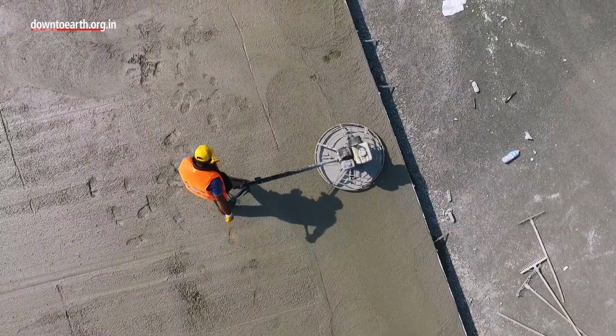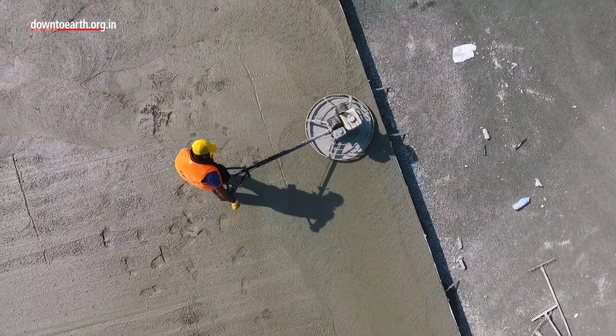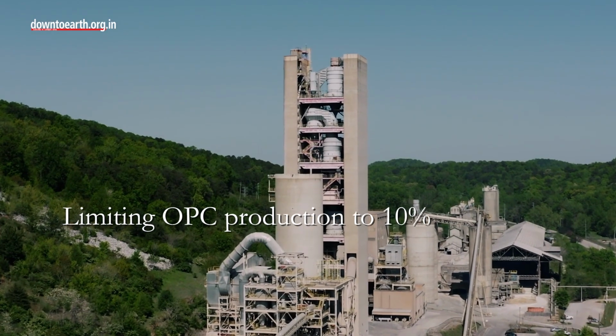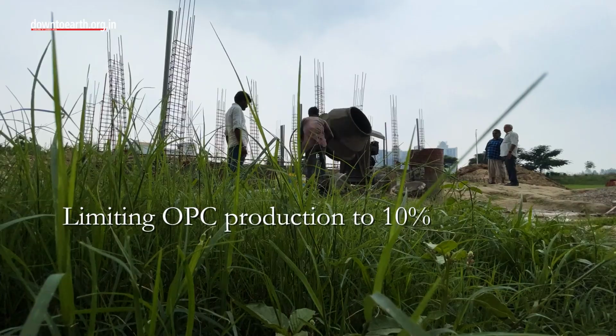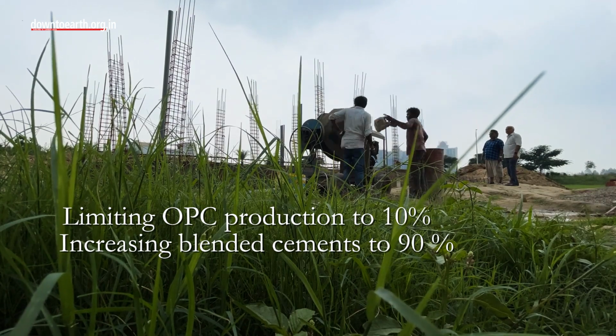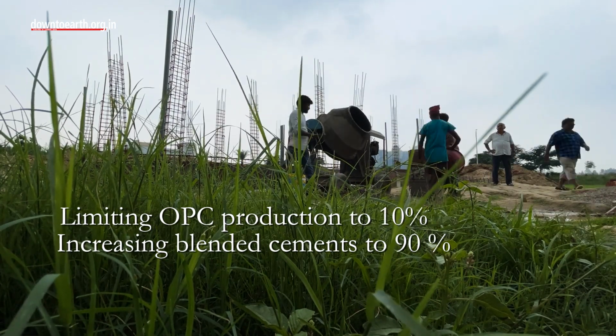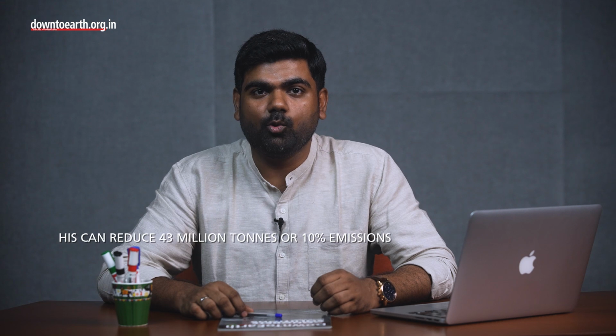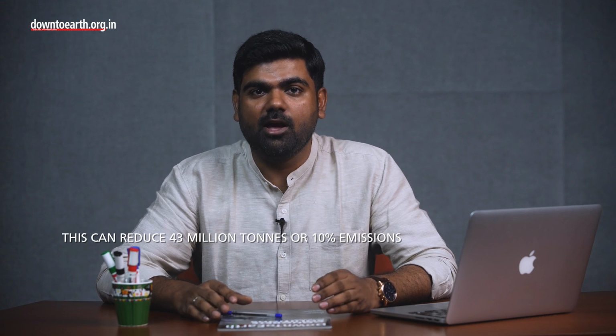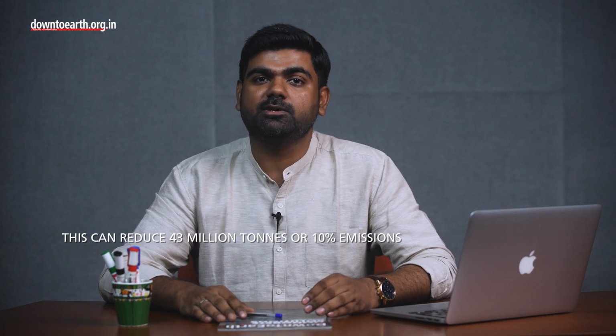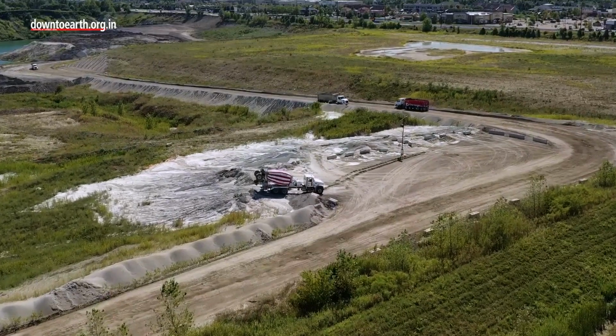CSE proposed a 2030 plan for the cement sector's decarbonization. It lays out 3 strategies with quantified targets and the amount of emission reduction the sector can achieve by implementing these strategies. First strategy is limiting OPC production to 10% and increasing the share of blended cements from 73% to 90%. CSE estimates this alone can reduce 43 million tons or 10% of the CO2 emissions as compared to the business as usual scenario.